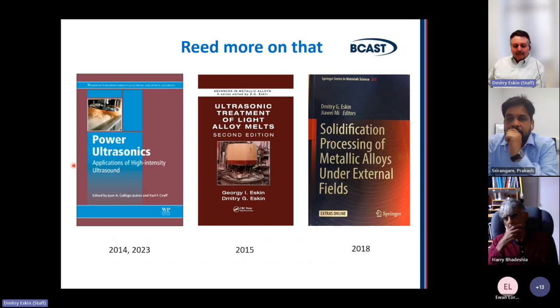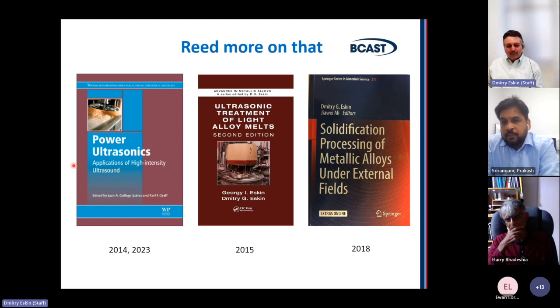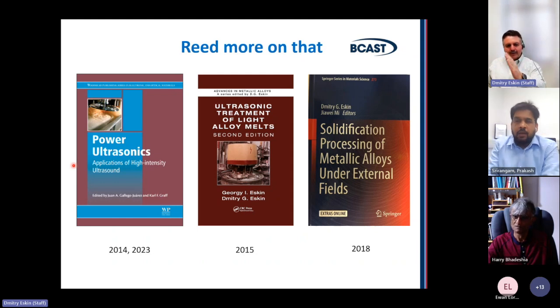Harry, this is a different area. This is called vibration processing. So if you don't want to deal with cavitation and ultrasound, you can of course apply low frequency, high amplitude vibrations, and then you can achieve some of the effects similar to what you have with cavitation. For example, you can achieve fragmentation. Yeah, but there are different mechanisms. It's mechanical fragmentation of weak solid material by inducing some waves in the melt, and then most likely by a fatigue mechanism, you will fragment this. There are studies on that.